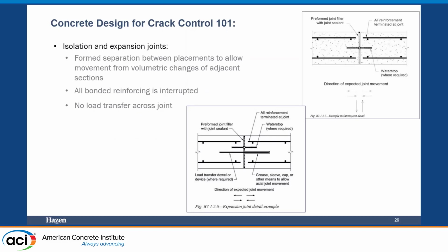So, isolation and expansion joints. Isolations are in the upper right, expansion joints are in the lower left in this graphic. With both of these type joints, you have a physical separation to abutting pours. There's a physical distance provided between the joint. So your isolation joints allow movement in any direction. You can move longitudinally in the plane of the wall. You can move perpendicularly. In the perpendicular direction, they're not connected. There's no reinforcing bonded that crosses the joint.